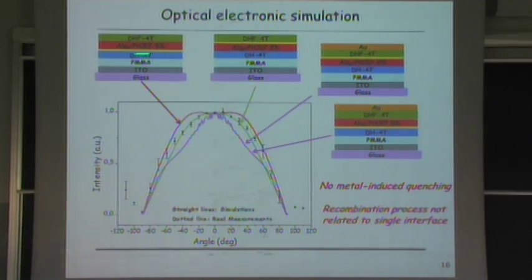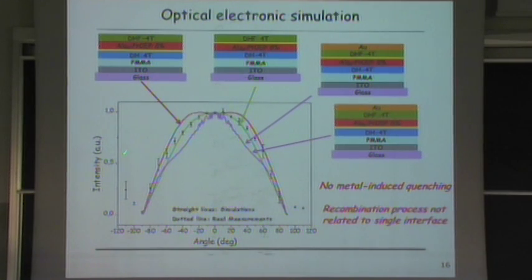structures. The yellow line is the distribution of excitons we put inside the device, and we saw that this pink curve is not present in our results. So we can conclude that there is no metal-induced quenching. And in the other two cases, there is a little bit of superposition here. So in practice, the process is not dependent on a single interface, but we think that the recombination process is inside the bulk of the material of the recombination layer.